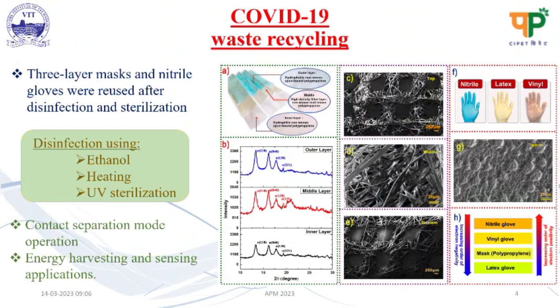Coming to the detailed analysis on materials, there are variety of masks and gloves available in the market. Here we selected three-layer mask and nitrile glove. Three-layered masks are made from polypropylene nanofibers. It has an outer hydrophobic layer to repel droplets and moisture, and inner light colored hydrophilic layer to absorb droplets from exhaled breath, and a middle filter layer.